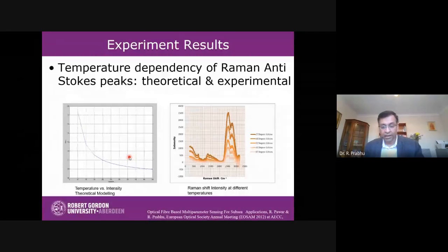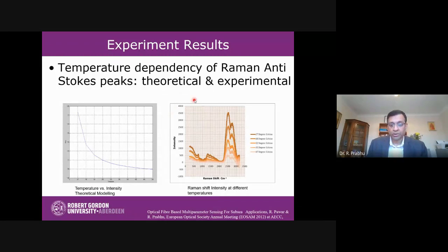One of my postgraduate students has been developing different types of glasses for sensitive measurement of temperature. She was studying the sensitivity and used a Raman spectrometer exciting at 785 nanometers while changing the glass temperature. You can see that for lower temperature, signal strength is higher. As the temperature increases, the signal goes weaker. So this follows a similar trend, and this can be used for temperature monitoring using optical fibers.